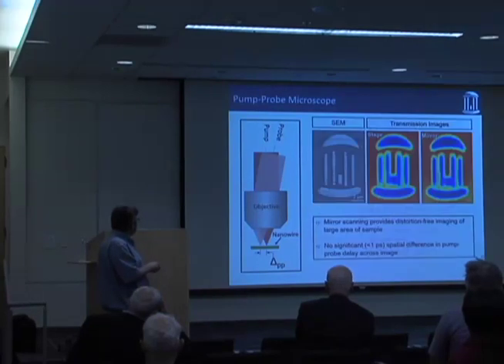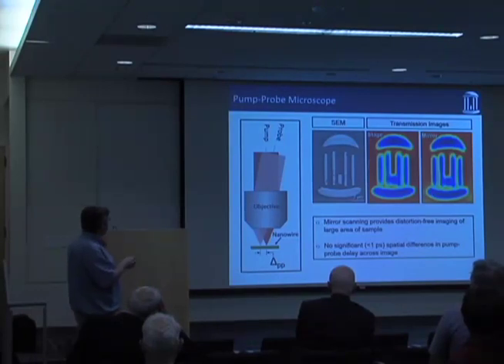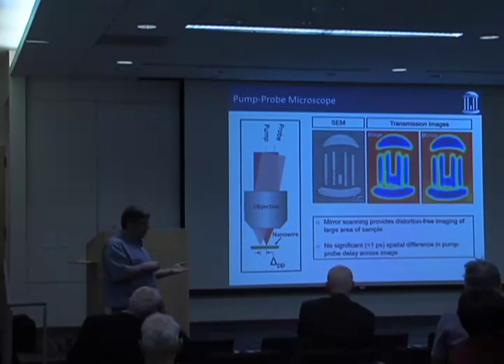And we can image with it. This is UNC's Old Well, and it's their icon, I guess. You can tell it's old because it's cracked. We have this little logo, and this was an image we took with the sample scanning XY stage. And this is what we get with our mirror assembly. So we can scan distortion-free across 10 or 30 microns or so, and there's almost no difference in the pump-probe delay across that image.